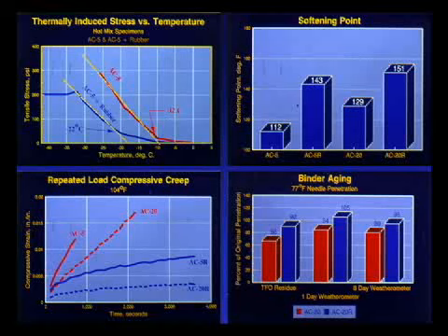Some might look at this and say that's not a very great change, but when we look at the temperature susceptibility of asphalts, this is very important. Even this is a log-log scale, so that's a very great change there. Here we see the different changes in tensile stress versus temperature. And what this tells you is what happens at cold temperatures. You can see that there's roughly a 10-degree difference in the property here. What that means is that in cold climates, rubber is going to perform quite a bit better, when you look at the 10-degree change that you get between asphalt rubber and the conventional binder.